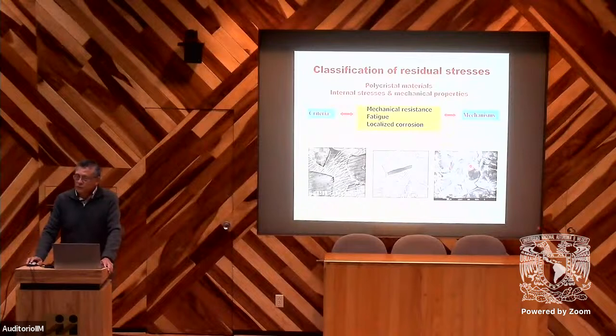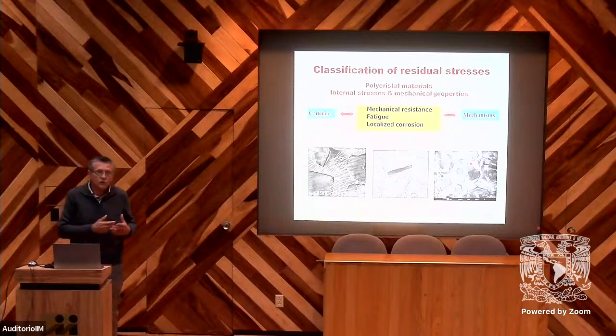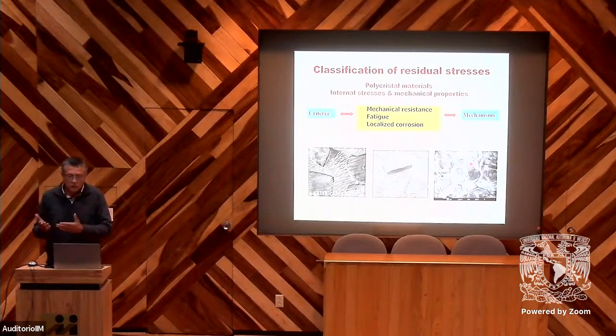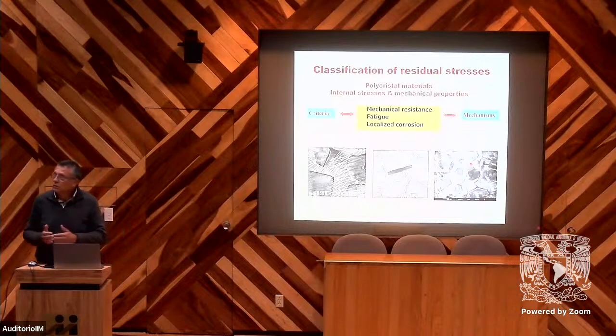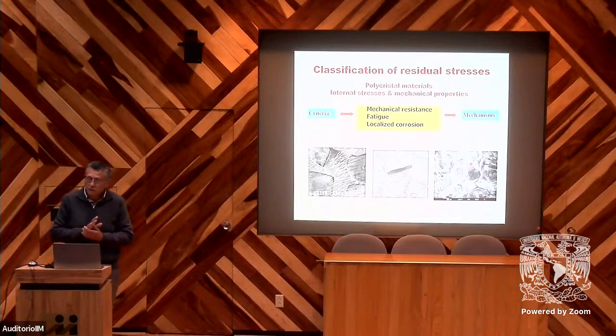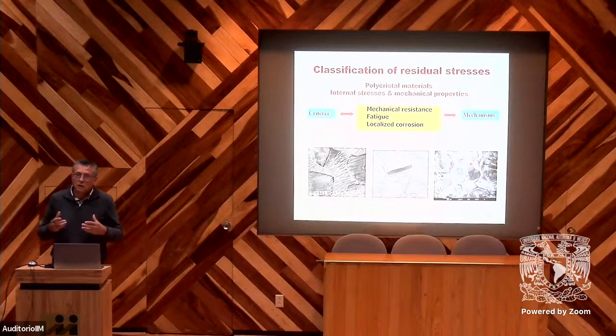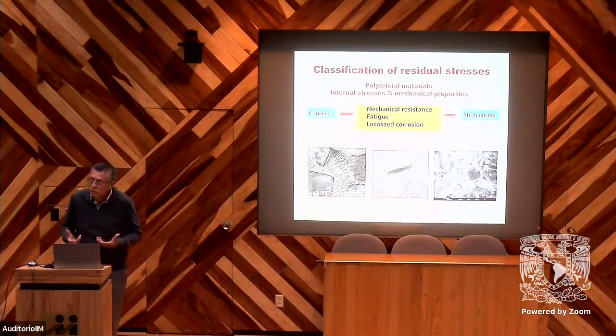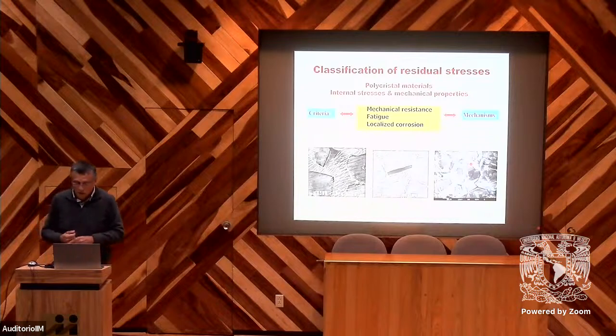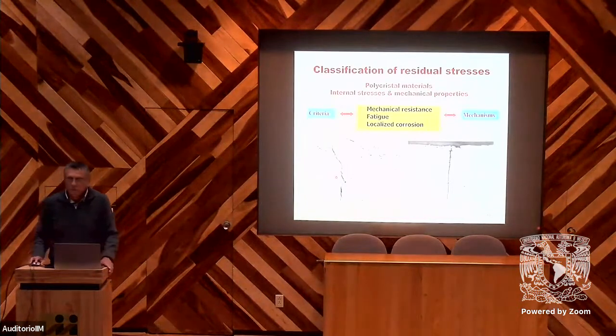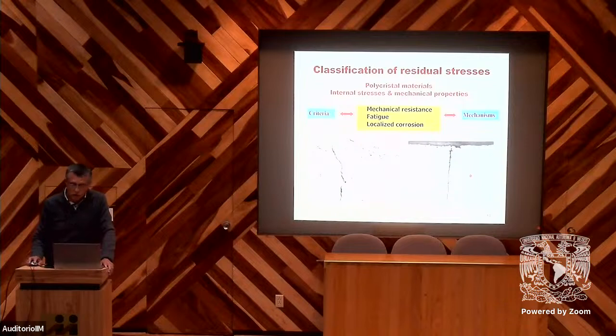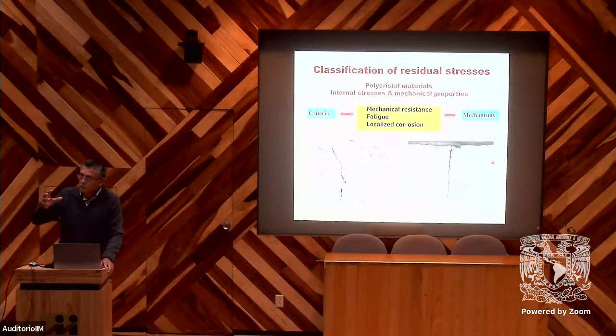And it can be very important to consider the different scales, because when we need to determine a criterion for mechanical resistance or for fatigue or localized corrosion, we need to understand the mechanisms of the deformation and also of cracking at the different scales. We can observe, for example, in this example, that we have cracking in only one phase in this duplex steel. We can observe also that cracks will occur in some grains due to their orientation.